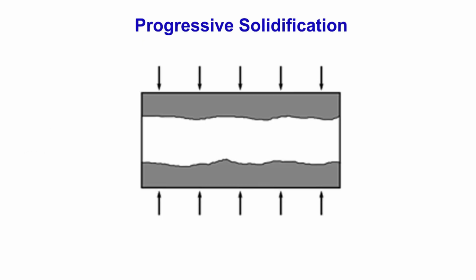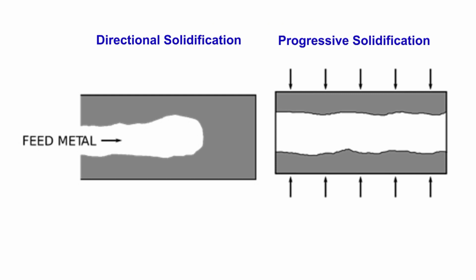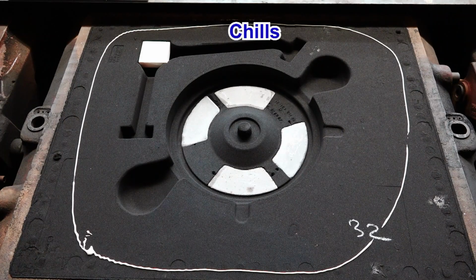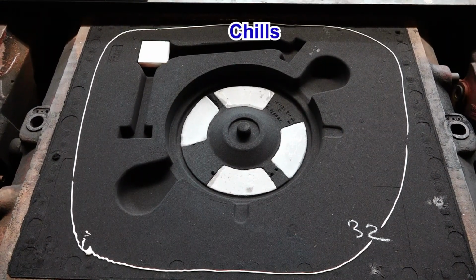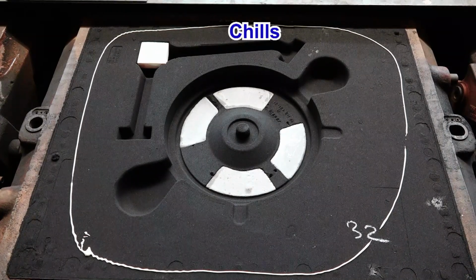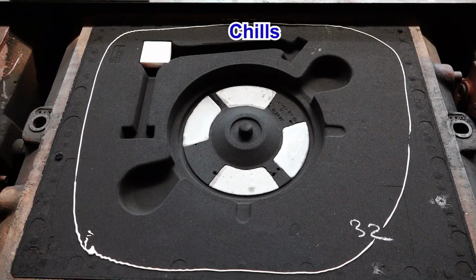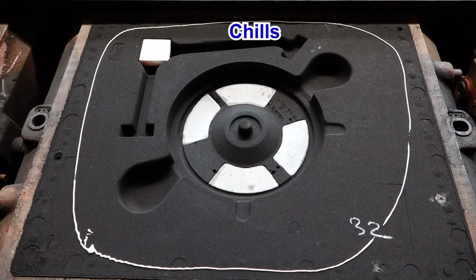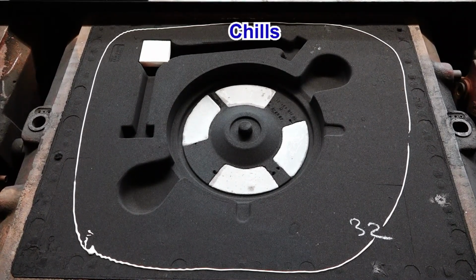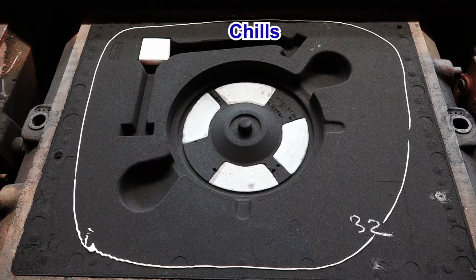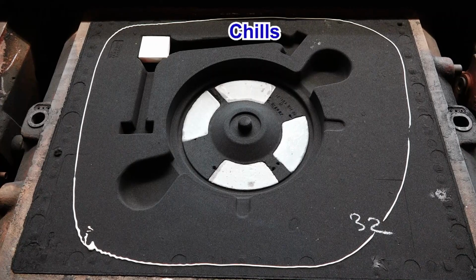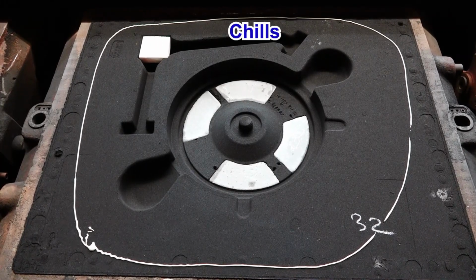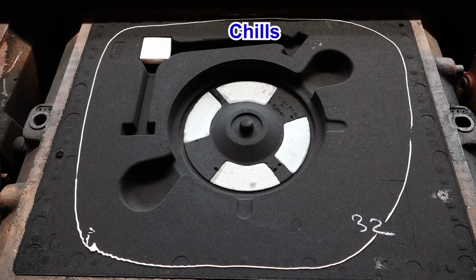If the solidification starts at the walls of the casting and progresses perpendicularly, it is known as progressive or parallel solidification. A shrinkage defect will occur when progressive solidification dominates the directional solidification. Internal and external chills are used to promote solidification when a heavy section of the casting is remote from the source of feed metal or when it is difficult to mold a riser in the required place. Chills are metal shapes used to speed up the solidification in heavy sections, thus permitting the shrinkage that takes place to be fed through adjoining sections.